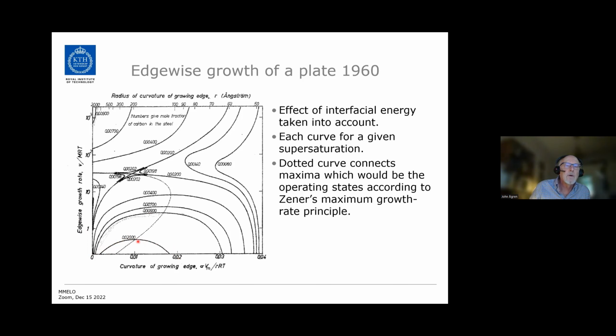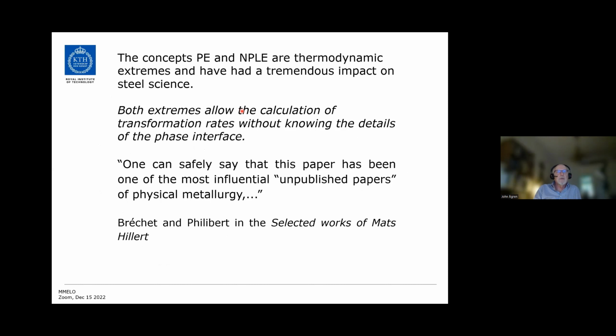And then we connect all the maxima for the different supersaturations with this dashed curve, because Mats Hillert applied Zener's maximum growth rate principle, which says that we would observe in nature the radii which have the fastest growth rate. But then you see here at some point, there is a critical point. And for supersaturations larger than that point, there is only one continuous curve. So Mats interpreted this as a case, if you are beyond that, you will get transition to a very fast reaction, which is essentially diffusionless. So I'll come back to this.